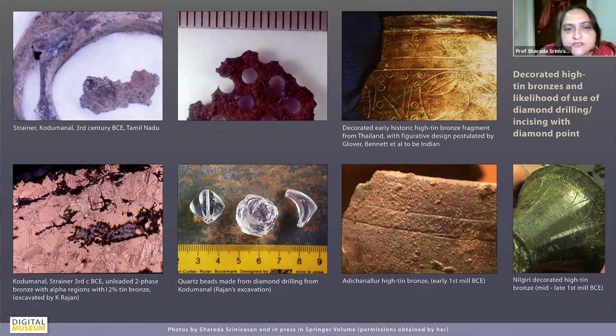So it's possible that these holes were being made by diamond drilling, and that had also been postulated with respect to the decorated early historic high-tin bronze fragment from Thailand, which had been examined by Glover and others. And of course, he had also postulated that that particular decorated high-tin bronze was directly from India, because it has a decorative figure on it. The figural representation is much more like what you would find in early historic India, whether it is Satavahana, Shunga, and so on. So the likelihood that this was Indian is what they postulated, and then it's found in Thailand. And that also seems to have been cut with a diamond wheel.